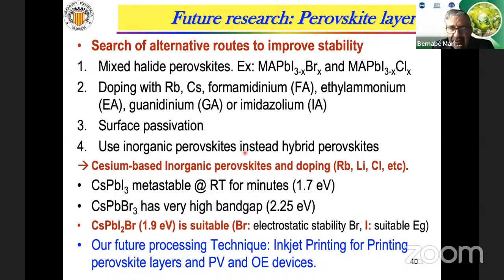And we are also using inorganic perovskite instead of hybrid perovskite. Inorganic perovskites are mainly based on cesium. And cesium can also be doped with several materials: rubidium, lithium, chloride, etc. So what happened? Cesium lead iodide is metastable, so it degrades very rapidly.